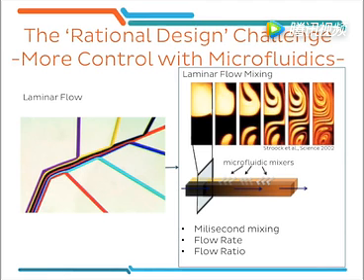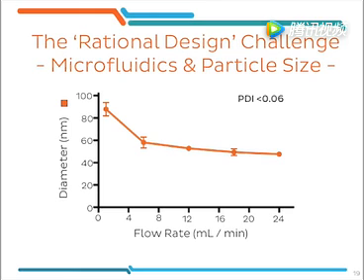Also, since we bring the fluids together in an inline manner, the ratio of the two fluids to each other remains constant during the mixing. Now, the mixing speed is directly influenced by the flow rate or the flow speed of the fluids in the microfluidic channel. And at a millisecond level, this mixing speed actually dictates how the single lipids assemble into nanoparticles.